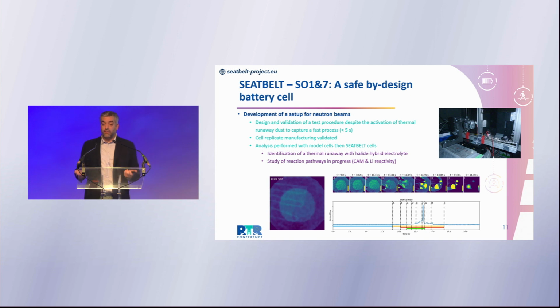The object we need at the end of the day is also a safe battery. Of course, you want to talk about materials, you want to talk about cost, but the consumer will be able to take and use this battery only if he knows that this is safe. And for that, we are developing kind of a new methodology related to safety, and we took advantage of the consortium, where we have CINEA and ILL, plus CNRS, and we developed, in fact, a kind of methodology using neutron imaging. Why neutron? Because neutron is very sensitive to lithium metal, so we can really image lithium metal during a thermal runaway experiment, and this has been done successfully dozens of times at ILL.